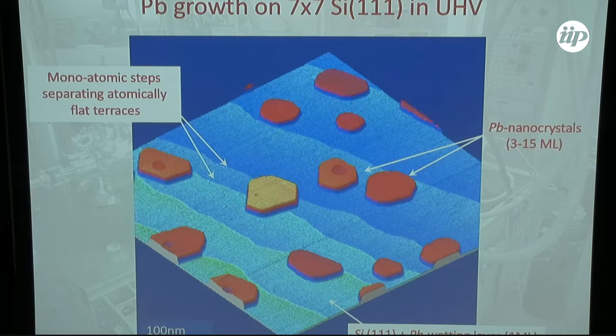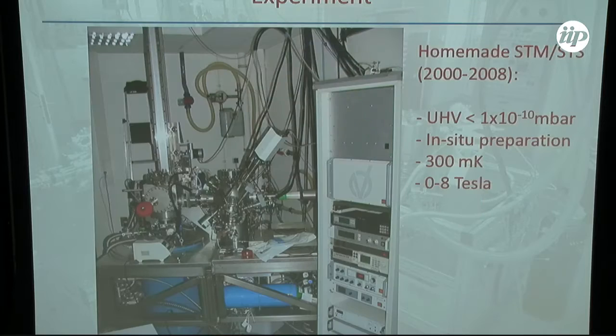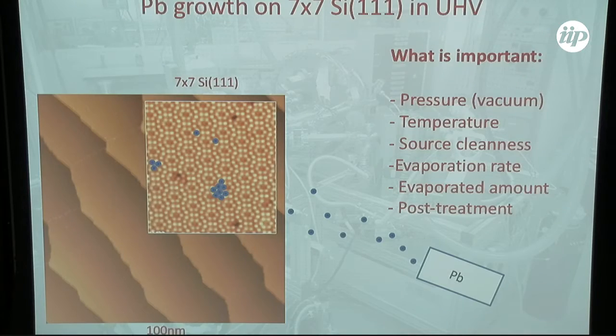And since we continue to deposit more atoms of lead above this monolayer, other atoms do not cover epitaxially the substrate, but they combine in islands. It is the so-called Stranski-Krastanov scenario in surface physics. Okay, so you have a very rich situation. To do this, we need ultra-high vacuum conditions, of course, and also an STM working at very low temperature. It is a homemade machine, etc.